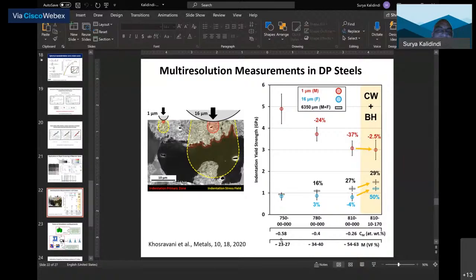But in our case, for the examples that we looked at, when you go to very, very small sizes, you get what are called pop-ins. In the sense that when you go to very small sizes, you're not able to establish a Frank-Read source. So you cannot get the smooth transition from elastic to plastic. It builds up until the zone size is big enough that it can actually release a Frank-Read source. And then suddenly you get a burst of plastic deformation. So there are size effects of that kind, but there are no size effects where, because I use an indenter of different size, I'm getting a different yield strength itself.